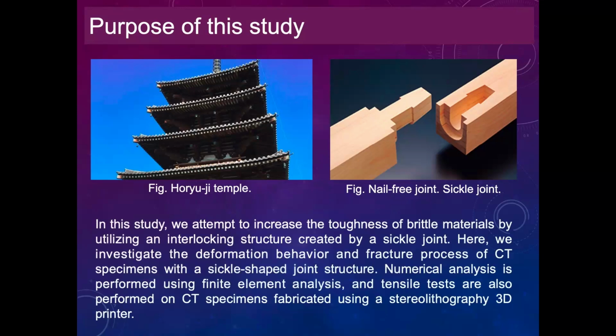In this study, we focused on this kind of sickle joint structure to increase the fracture toughness of brittle materials, by utilizing the interlocking structure created by the sickle joint. We investigated the deformation behavior and the fracture process of CT specimens with the sickle-shaped joint structure. Numerical analysis was performed using finite element analysis, and a tensile test was also performed on the CT specimen fabricated using stereolithography 3D printers.